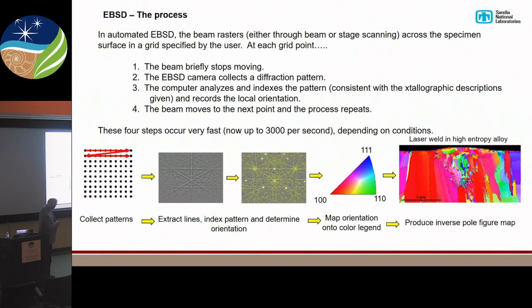We index the pattern. We then, if we're plotting out orientation maps, everybody likes pretty color pictures. They end up on covers of journals, and they do make some nice, pretty pictures, I'll show you. But we can then plot the orientation based on this color scheme. This is a high entropy FCC alloy. This is a laser weld in that alloy right there. You can see that.